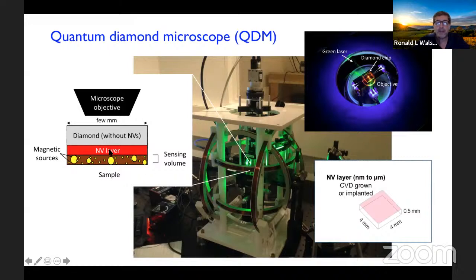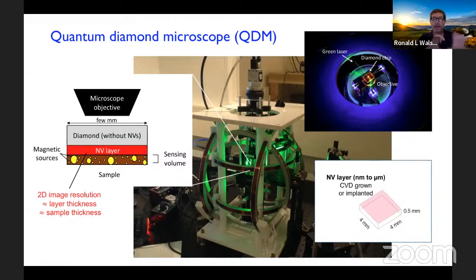So you might be taking a field of view image. Your field of view might be a few millimeters or a few hundred microns. And the thickness of the sample of interest will set the NV layer that you want. So your 2D image resolution is often, yes, going to be limited by diffraction and your optics to maybe half a micron or something like that. But sometimes it won't be as good as that because the sample might be thicker. The sample might be 2 or 3 microns with magnetic features that are 2 or 3 microns, for example. And so you will choose your NV layer to be similarly 2 or 3 microns thick in that case.